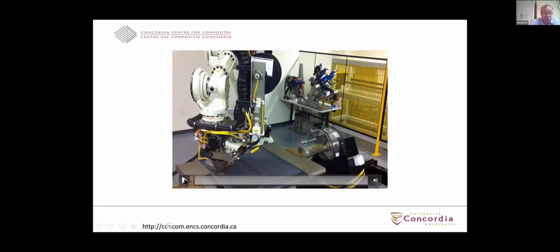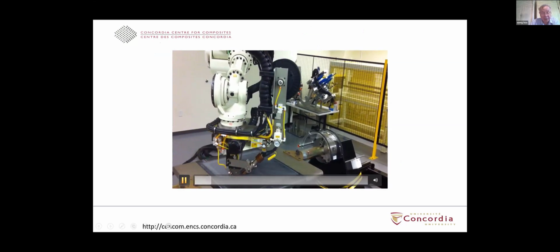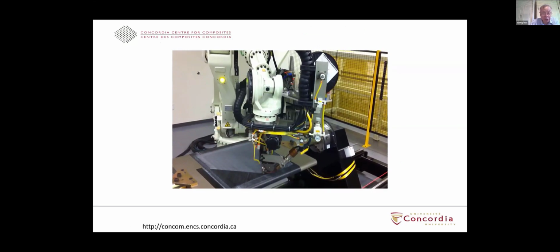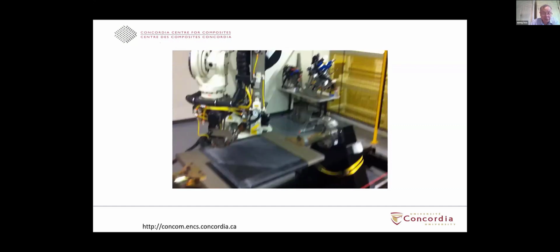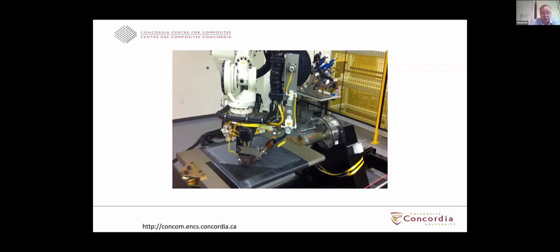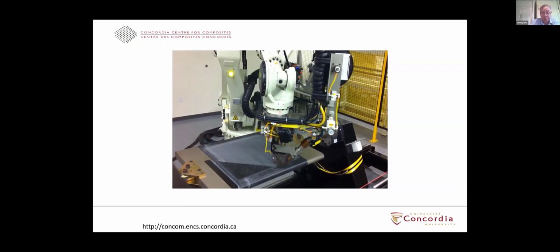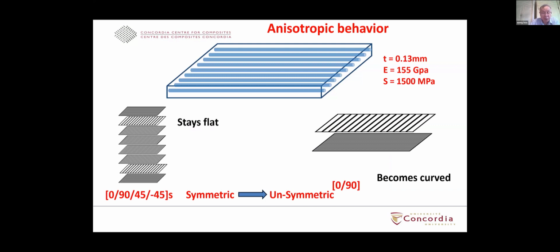And in this case, the way that we make the composite is that we use an automatic fiber placement machine. This machine can lay down continuous carbon epoxy fibers along a certain orientation, and you can vary the orientation of the fiber to make different layup sequences. The main mechanism that we use for the printing of composite is that we use unsymmetric laminate. Usually most people doing composite manufacturing use symmetric laminate. Symmetric means that you have a layup sequence that is symmetric across the mid thickness of the laminate. For example, you have the layup sequence of 0, 90, 45, minus 45, and you put the S for symmetric. That means the 4 layers below the midplane are exactly the same as the 4 layers above the midplane. The reason people want to use symmetric laminate is that they don't want the laminate to distort.